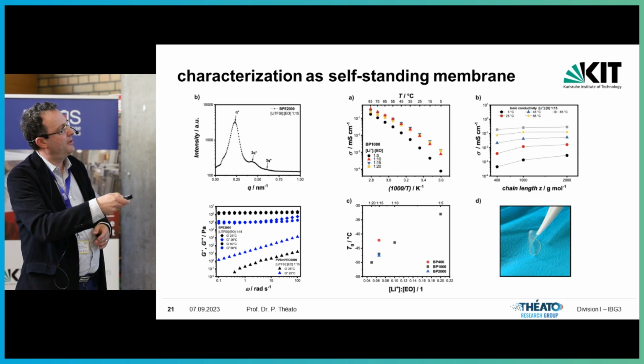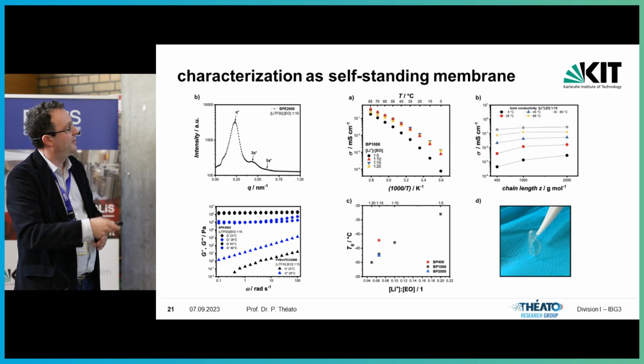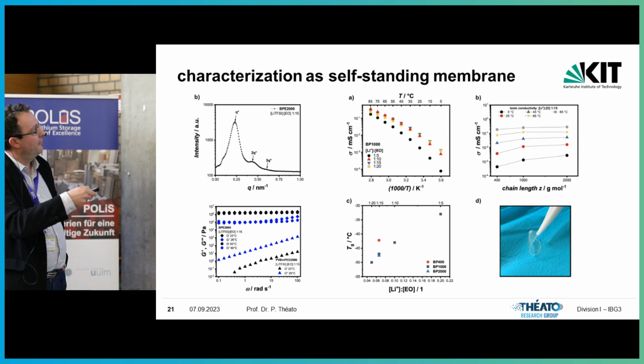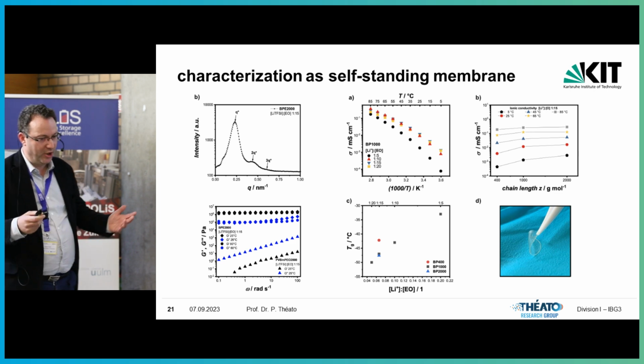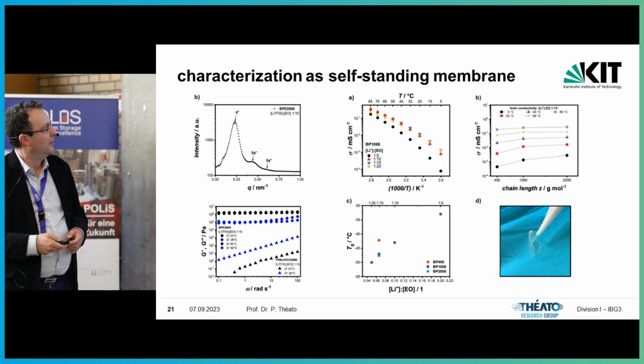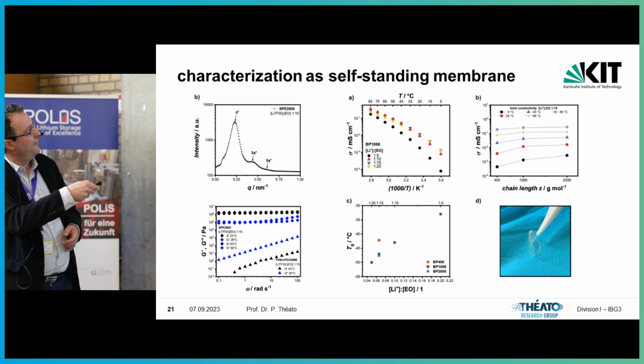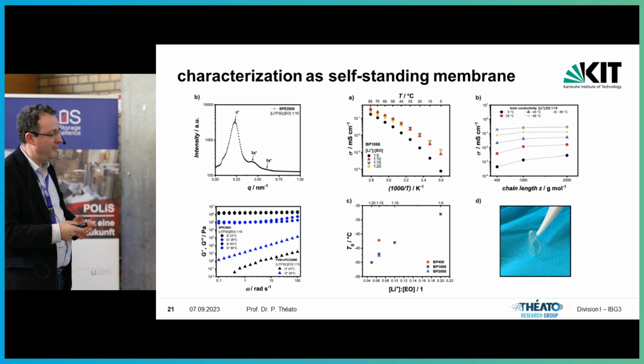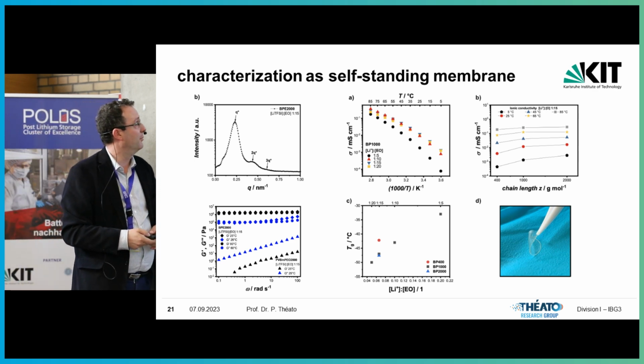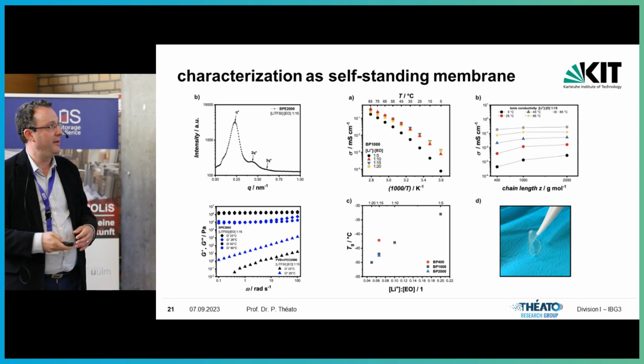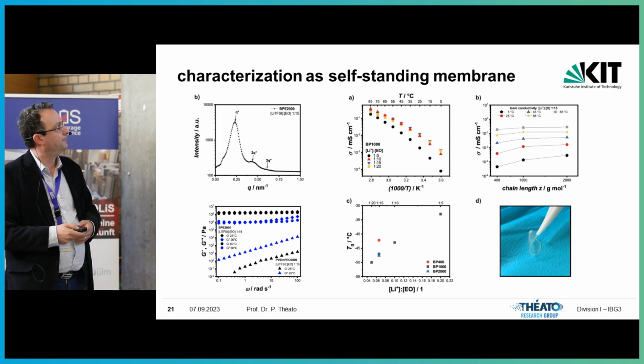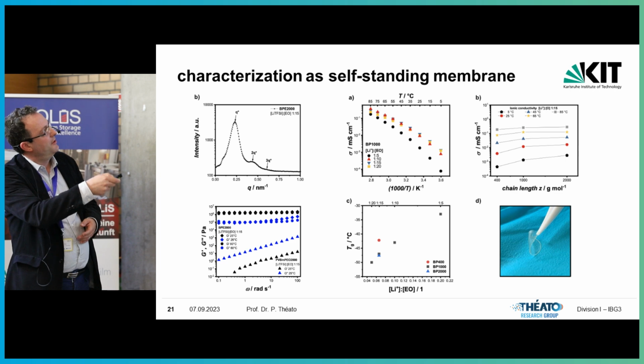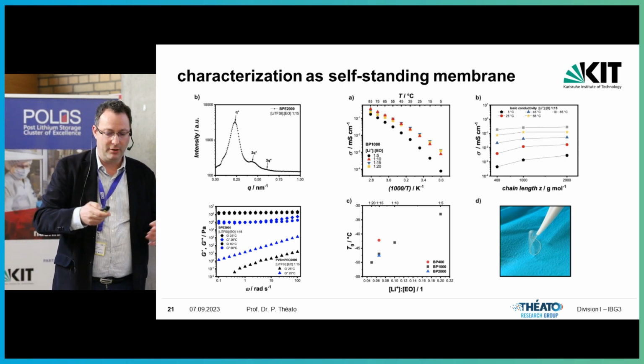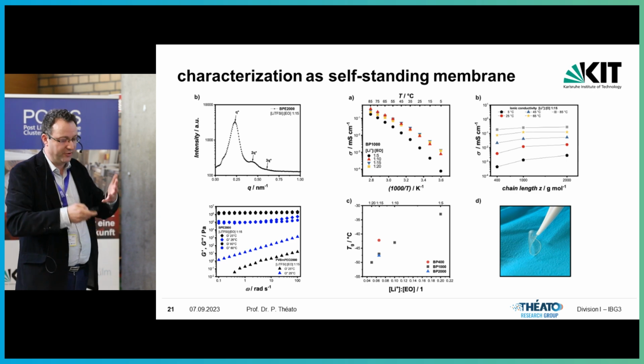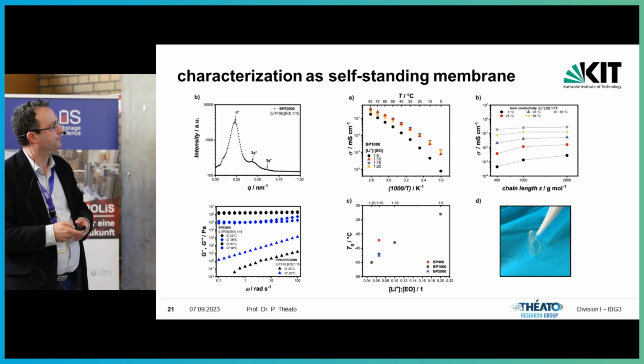You can look at the conductivity, of course. That depends on the chain lengths and the temperature, the typical thing you would expect. And you can really characterize the mechanics. This is the rheology data for just the homopolymer without the polystyrene. As soon as you put in polystyrene, you can see that you get a ramp up of at least 5 orders of magnitude in the G prime and G double prime values. So it's a dramatic change in the mechanics, and that's what we can utilize. And of course, conductivity data still looks very good, even though now you have 50 volume percent of something else in there, but it's just there in order to provide the mechanics.